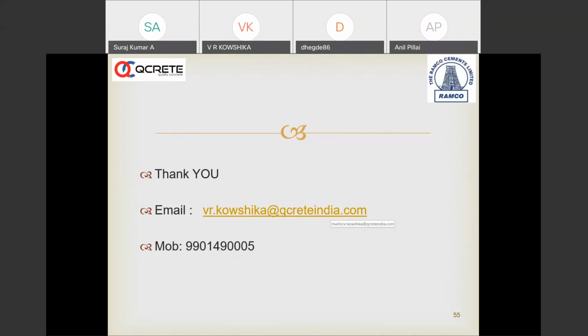The only thing that we can do, that we do regularly in a ready-mix company, is, as soon as the fly ash comes into our plant, we check the moisture. Moisture should not be more than 1.5%. And then we check the fineness on 45 micron sieve. This is well defined in IS 3812. IS very clearly says if the retention is more than 34% on 45 microns, we cannot use that fly ash for structural concrete. So when the truck arrives, we can do this test on each bulker, each fly ash before receiving.